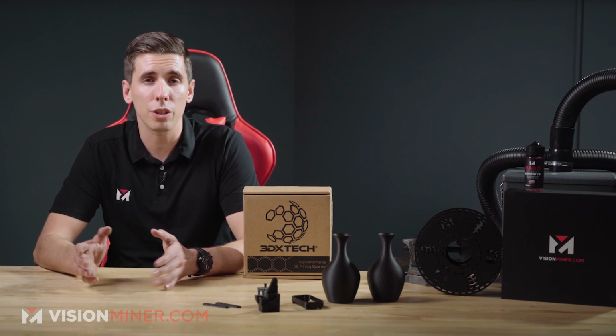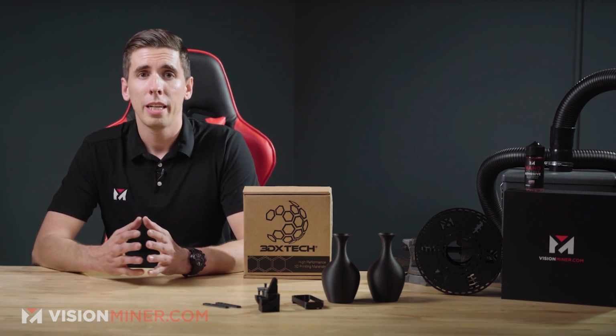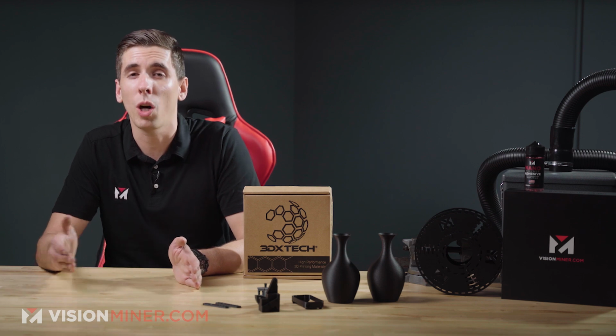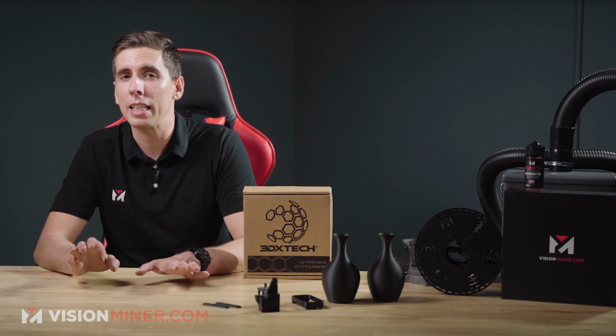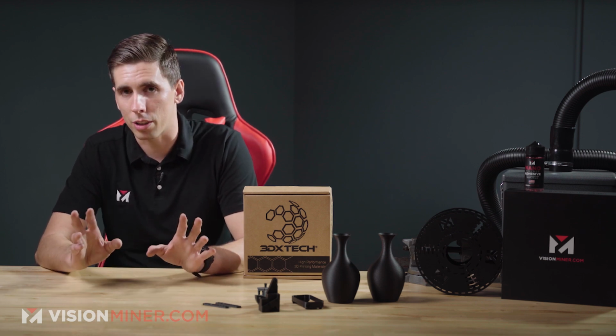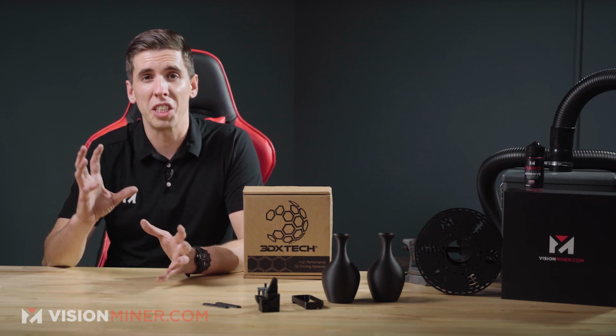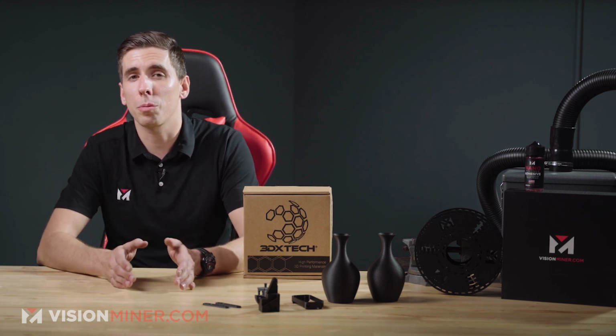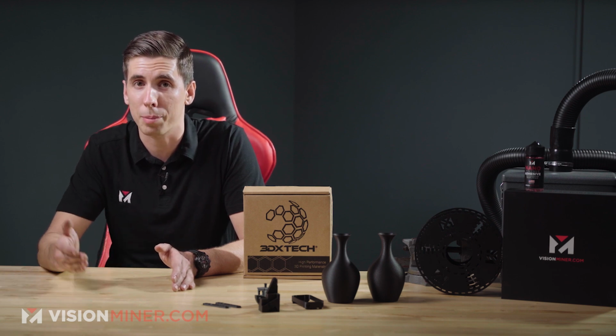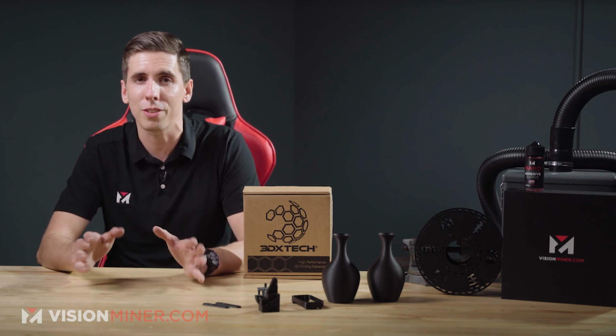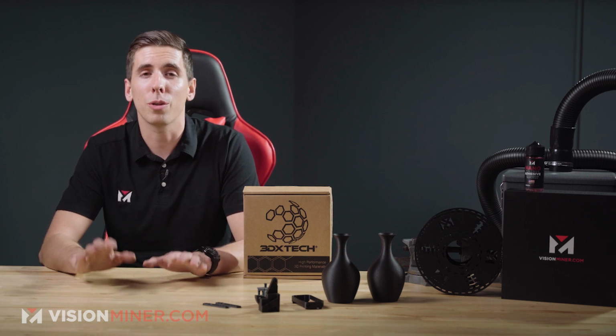Now, some basic strength specifications. In tensile strength, you get around 70 megapascals, and a tensile modulus around 6,200 megapascals. But keep in mind, the way your part's designed, firstly, and the way it's printed, like the orientation at which it's printed, is going to have a dramatic effect on strength in your application. You always tend to lose a little bit in the z-axis depending how it's printed, so keep that in mind.